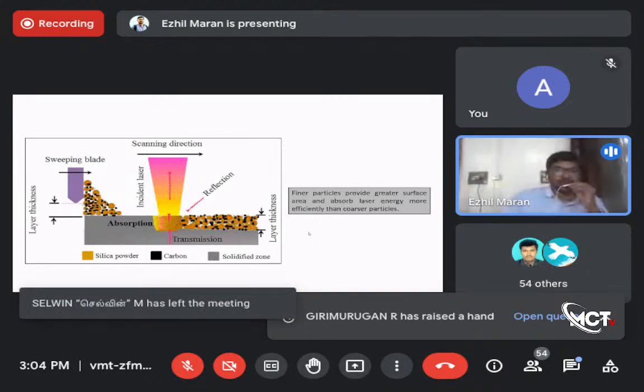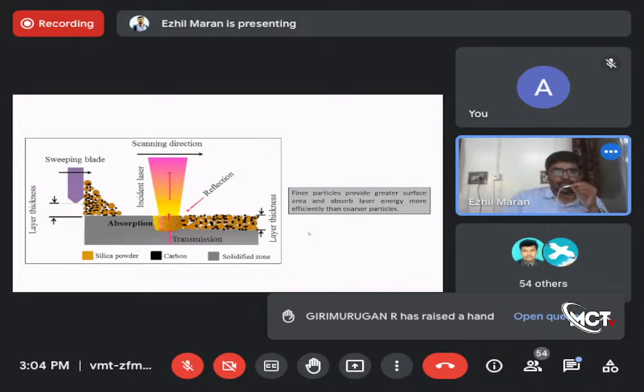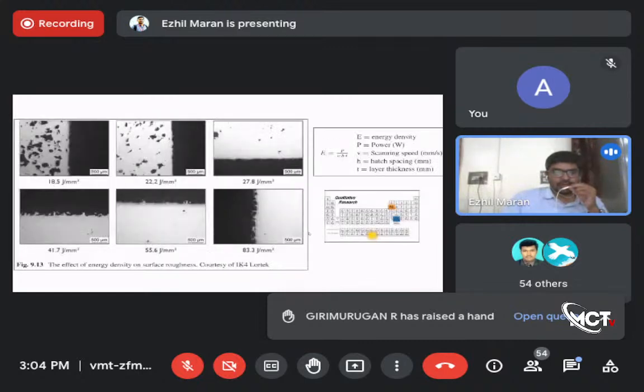In this picture, you can see the material is printed using various laser energies: 18.5 joule per mm cube, 22.2 joule per mm cube, 27.8 joule per mm cube. So the laser energy is increasing. At lesser energy density, at 18.5 joule per mm cube, you can see a lot of porosity inside the material. The powder is not completely fused. They end up in a porous structure. So that is not what I expected.